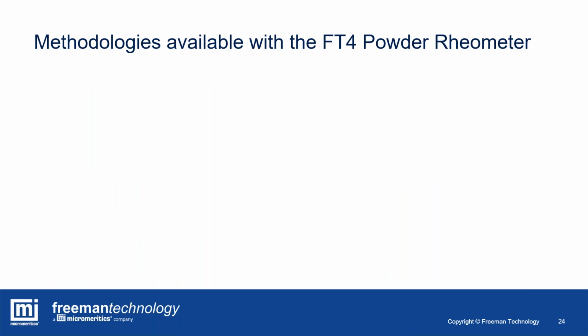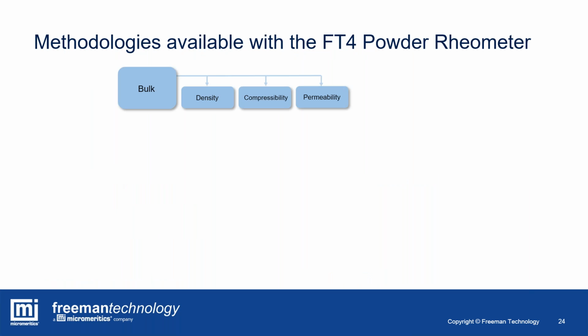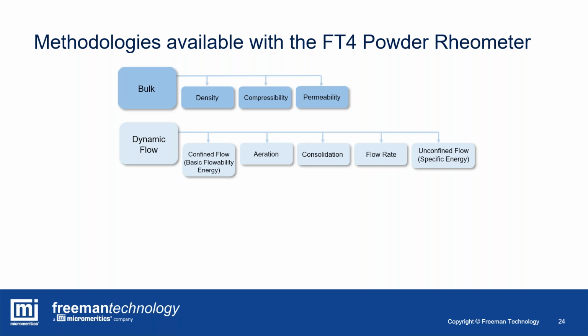So methodologies with the FT4 are quite diverse. We have what we call bulk characteristics such as density, compressibility, and permeability. We have a dynamic flow, which is allowing us to look at how powders behave in a confined state. So being forced to flow, a bit like in a feed frame of a tablet press, the paddles are forcing the material around, and that's a basic flowability energy measurement, as we would call it. We assess how the flow energy changes when you aerate the material, when you consolidate it, when you impose flow at different flow rate or strain rate conditions.